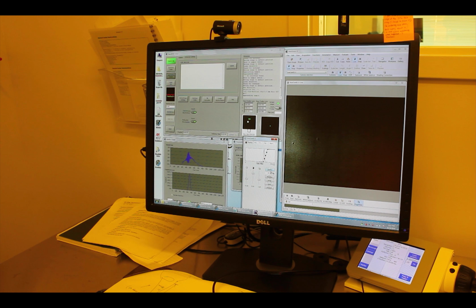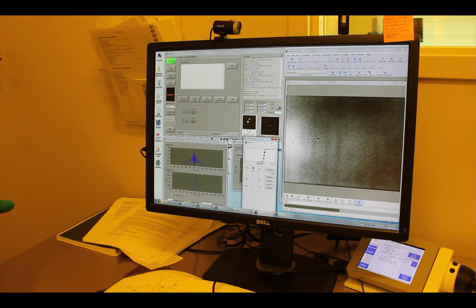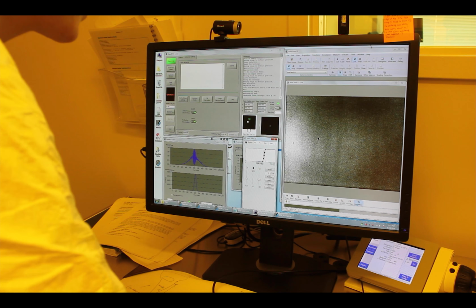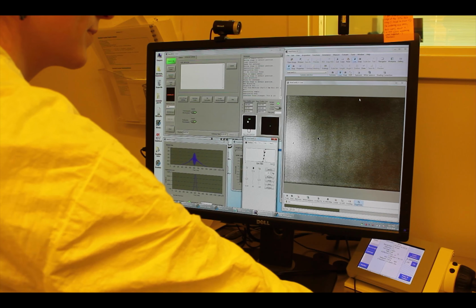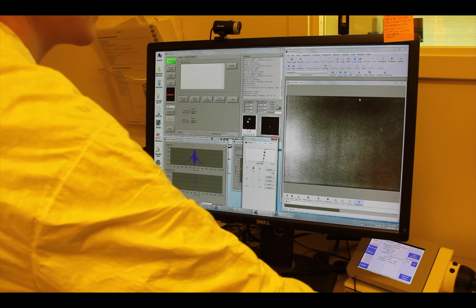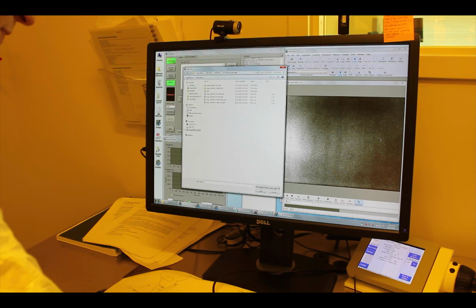The first step is to approach a sample and dip it into the photoresist, which is what we're doing right now. We're dipped into the sample right here. You can see the surface of the silicon. And so if I move around, you can see small pieces of dirt that I didn't do a very good job cleaning off here. So I'll load a job, which is the job file, this DNA job that we have here. And before it starts printing, the laser calibrates. So this is to make sure that the power that we're using every single time is the same.